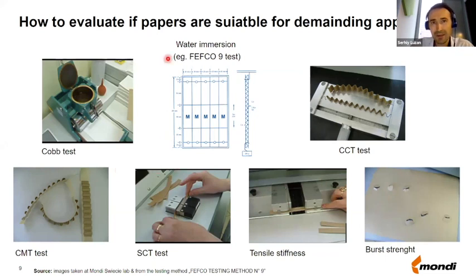Then, at least in Europe, some people are doing the test called FEFCO 09 test, where they take a piece of corrugated board, they put it on a hook, and then the whole construction is immersed into the water. Then you make two cuts, and on the bottom you hang a weight, and then you measure the time, how long it takes for the corrugated board to break. Actually, this test is primarily designed to evaluate not the paper strength and not the board strength, but the strength of the glue line, and to look at the quality of the gluing between liner and fluting. But still, some people are also comparing paper based on this test.